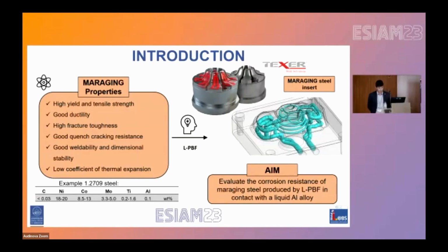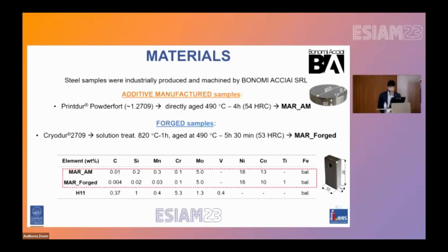So the aim of this work is to evaluate and compare the corrosion resistance of maraging steel samples in contact with molten aluminum produced by both the L-PBF technique and by the conventional route. The samples under investigation were industrially produced. As regards the L-PBF samples, they were produced starting from a commercial powder, namely Printdur Powderfort, that is similar to the 1.2709 alloy for the obtainable mechanical properties, but with a slightly different chemical composition.